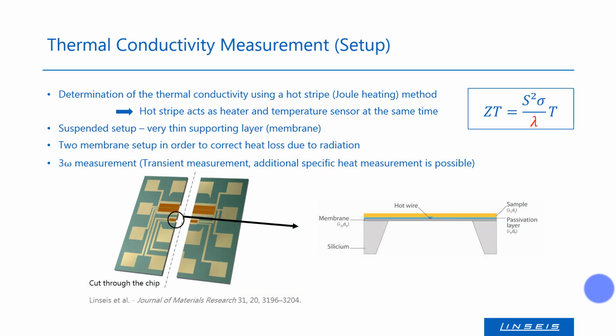Now, if we have a more detailed look into the thermal conductivity measurement, we can see the two membranes with different areas. If we cut through the chip and have a look from the side, we get the cross-sectional view, which can be seen on the right side. Each membrane has a hot wire aligned to the middle axis, which we use for heating, but also for temperature sensing. For the measurement, we apply a known heating power to the hot wire, which causes a temperature rise in the middle.